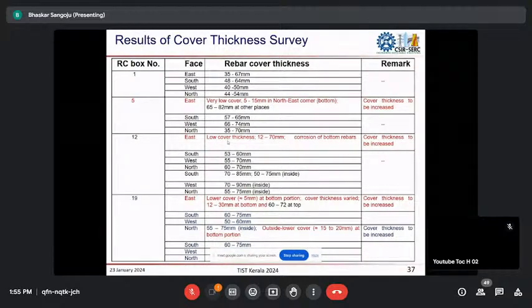This is the cover thickness profile, with different box numbers and faces: east face, west face, south face, and so on. We made a grid and measured the cover thickness. In some places, for example RC box unit 5, the cover is very low, 5 to 15 mm, whereas the required is 75 mm. This is where the durability issue will come. As we know, if the reinforcement is not protected adequately, corrosion will initiate very soon.